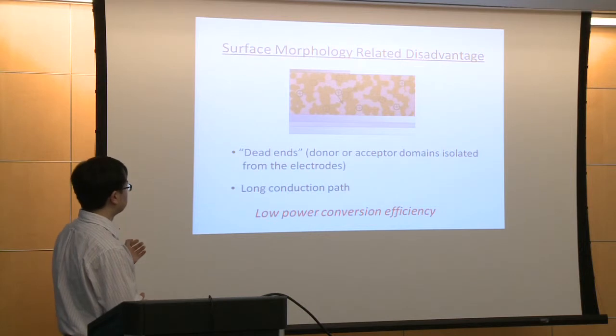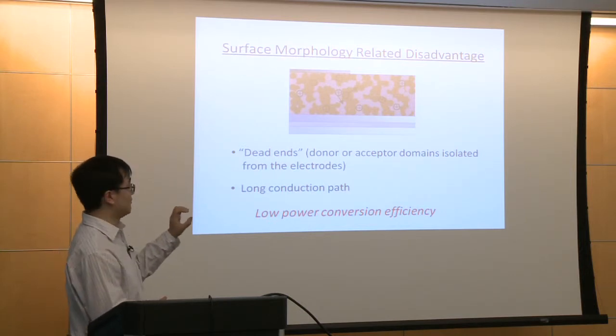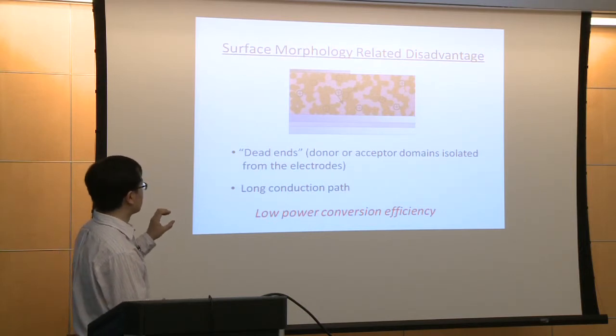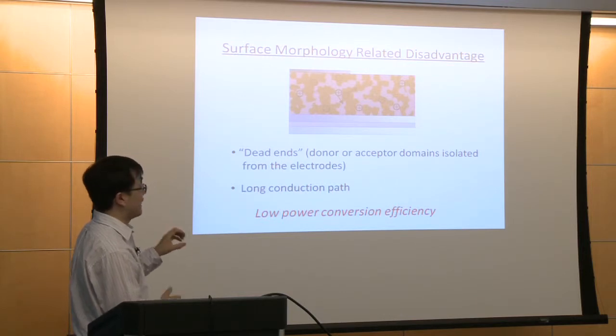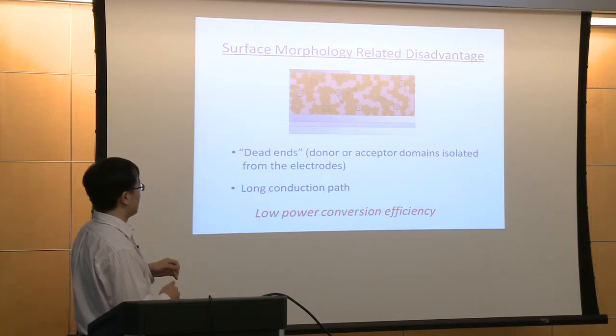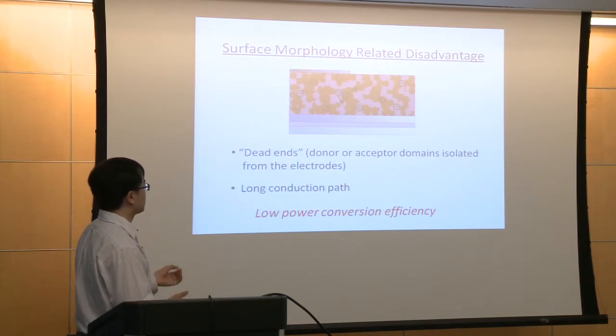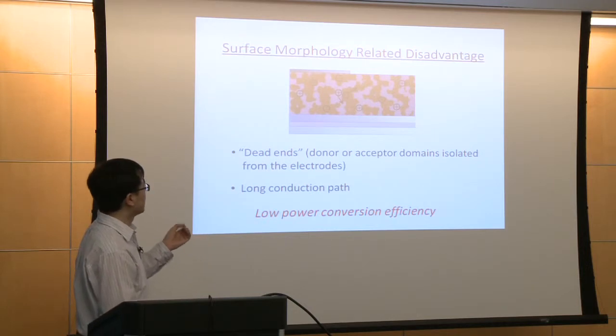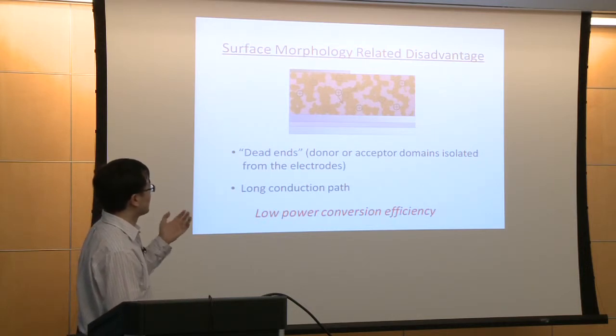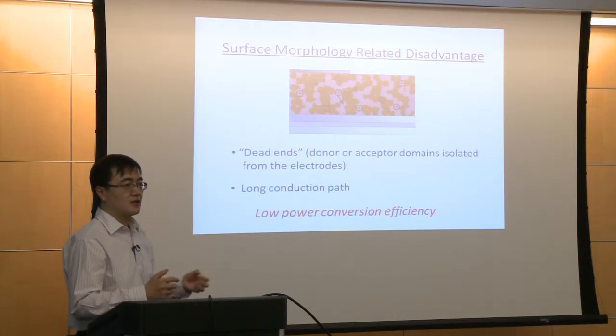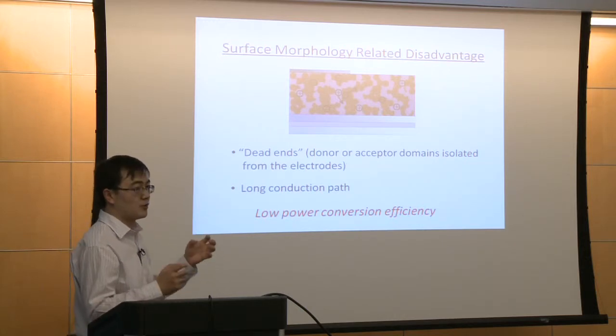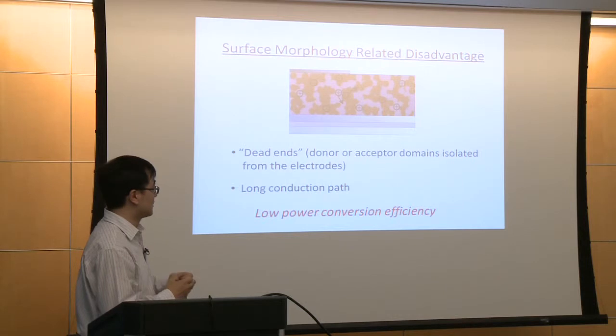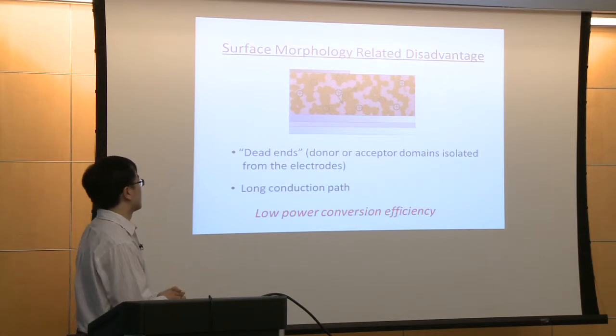As you can see, the structure within the active layer is very disordered, which means the donor or acceptor domains are isolated from the electrodes, and we call them dead ends, which means the electrons and or the holes cannot reach the electrodes on top or on the bottom. And if they cannot reach the electrodes, they will recombine as excitons. And then, by lowering the energy, they go back to normal. So nothing happens here. This is one problem.